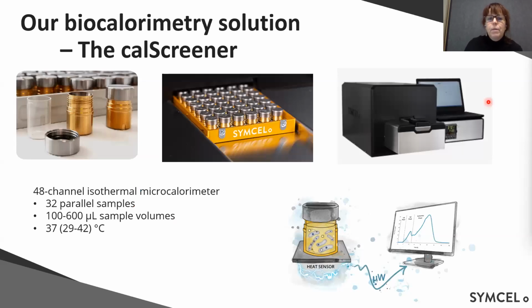So our biocalorimetry solution is the Cal Screener. It's a 48-channel isothermal microcalorimeter. You can run 32 parallel samples in this. Why it's not 48 is that all sensitive calorimeters need to have a reference. So we're measuring against a reference, and this particular calorimeter will have 16 references to measure 32 samples.